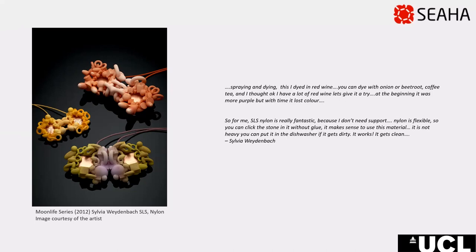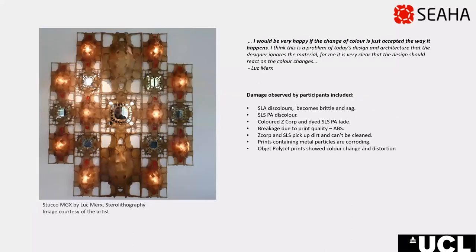Most 3D printing materials are sensitive to moisture and solvents, so hydrogels and tunable organogels could hold promise for safe and controlled cleaning. Knowing the thermal behaviour of polymers and their coatings is also important when considering storage environments such as cold storage, where potential shrinkage could lead to delamination. Another interesting observation was the acceptance of colour change over physical damage: only 34% agreed for discoloured works to be reprinted, and some designers factor in the tendency for the material to yellow as part of the design.